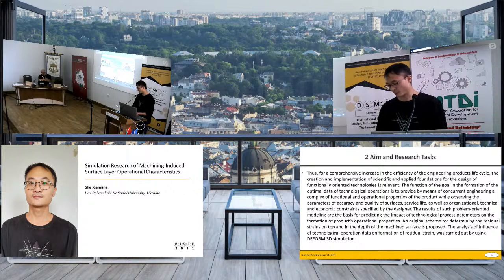The results of such problem-oriented modeling are the basis for predicting the impact of technological process parameters on the formation of products' operational properties. An original scheme for determining the residual stress state and the depth of the machined surface is proposed. The analysis of the influence of technological operation data on the formation of residual stress was carried out by using DEFORM-3D simulation. Next slide, please.